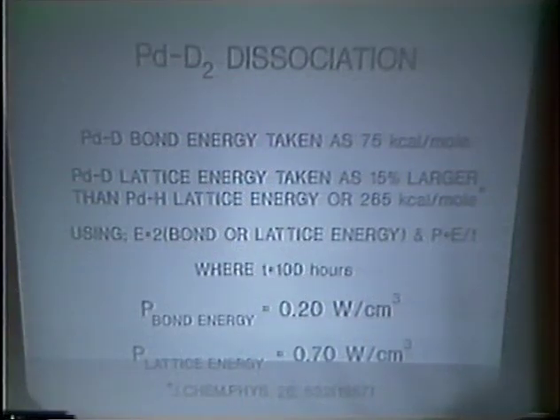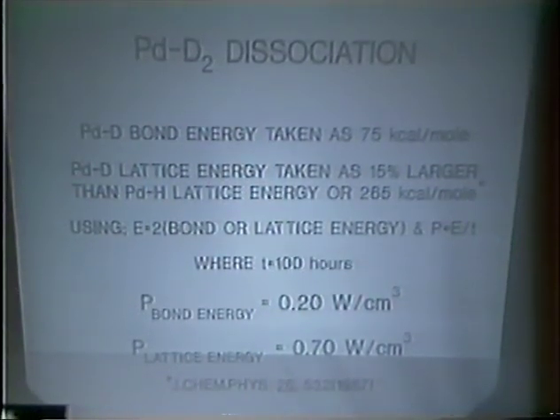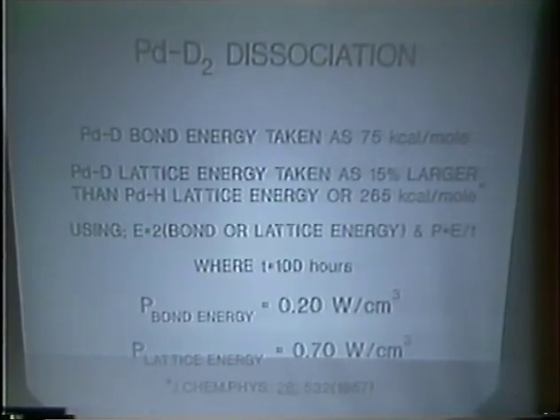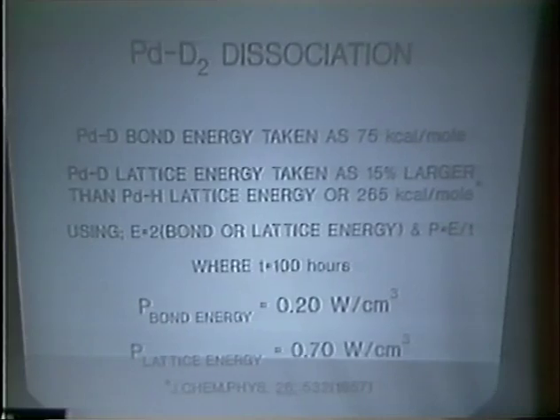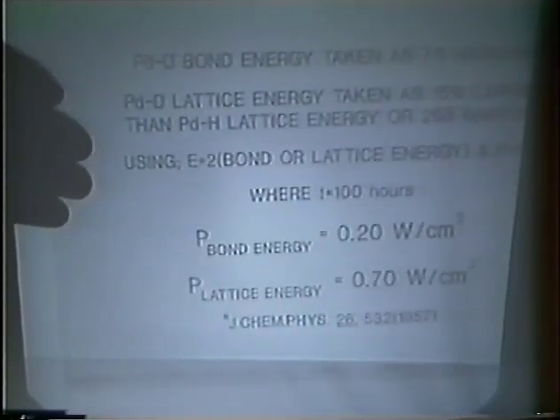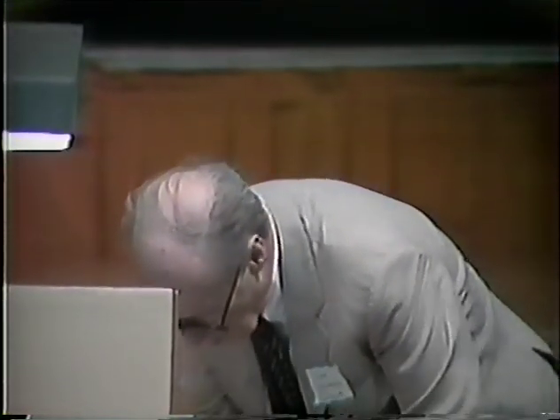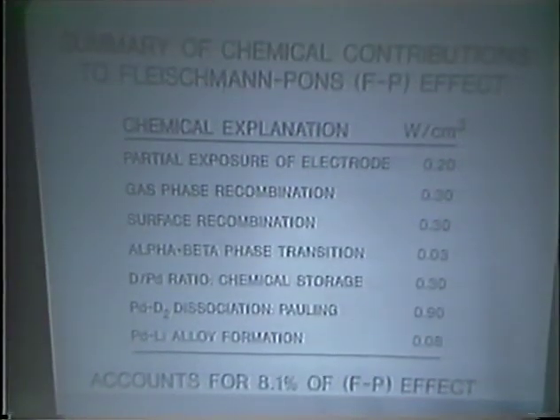We took the bond strengths of PdD2, and then we looked at a hypothetical lattice of PdD2, and we did all sorts of things to get numbers which might up the value. But the extreme we could get with that one was 0.7 watts per cc, with the doubt as to whether it's qualitatively a goer. Well, the chairman is telling me I must stop, and therefore I will put this last one on, which summarizes the various calculations. And I think I can say that the only one that leaves me with some fear is recombination, perhaps.